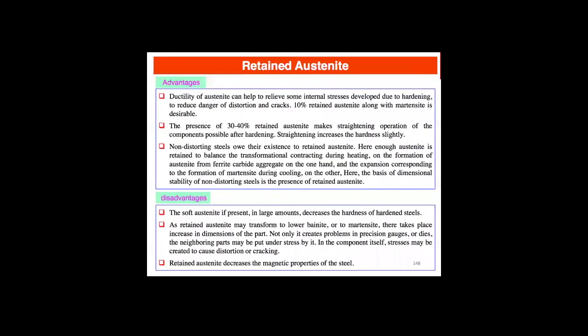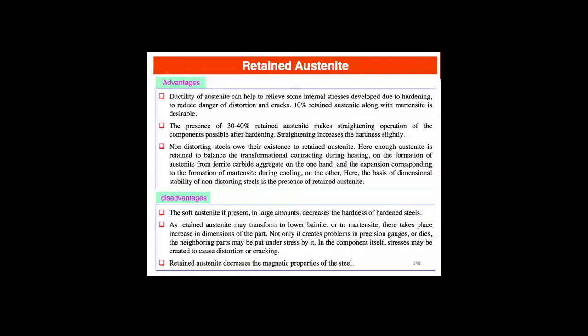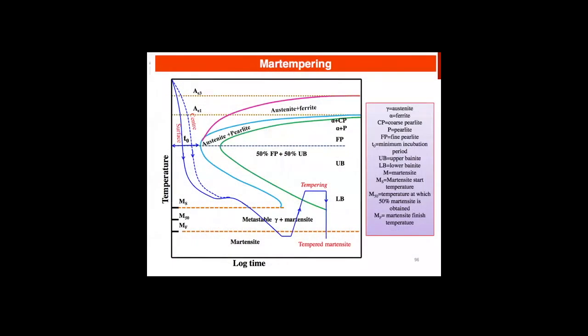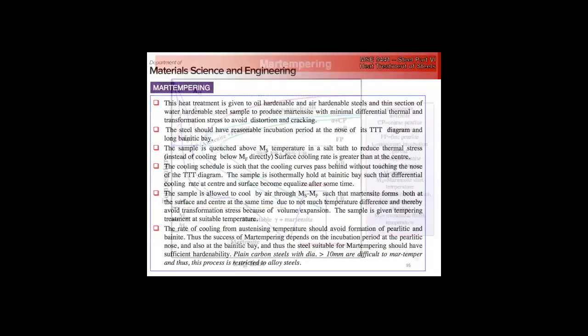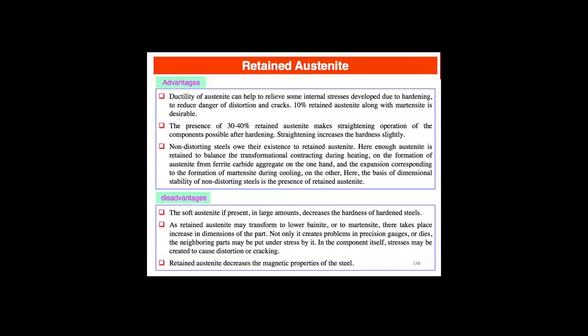And then, as we've mentioned, if you can't quite miss everything, or you can't cool below the martensite finish temperature, right? Some alloys have a martensite finish lower than room temperature. So if you can't actually get there, we're going to have retained austenite, right? In some cases you want retained austenite, other cases you don't.